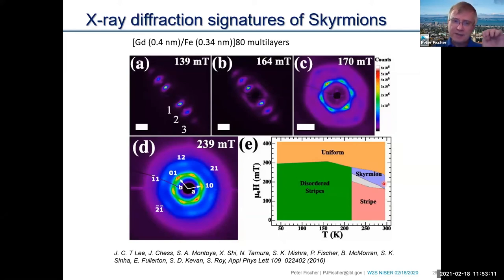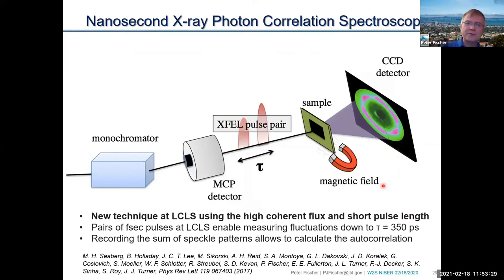So this was, again, the pre-experiments that we did. And then we said, okay, what's happening to the dynamics right at this transition from a stripe phase to a skyrmion phase? Is there anything specific? Is there anything different between a stripe and a skyrmion phase? And to study that, we went to Stanford and used what's called X-ray photon correlation spectroscopy, which allows us to characterize ultrafast, nanosecond fluctuations with a spatial resolution given by the length scales existing in the diffraction pattern.